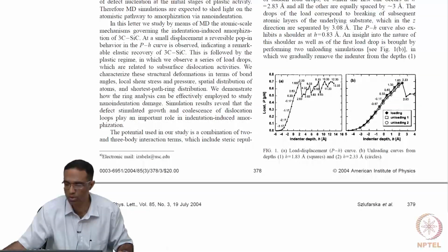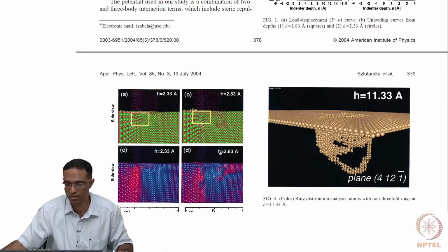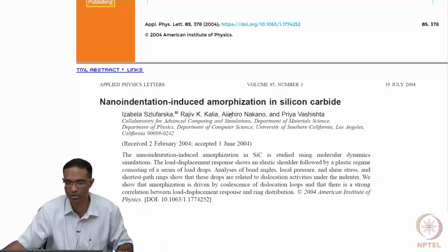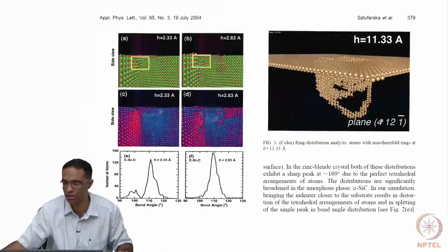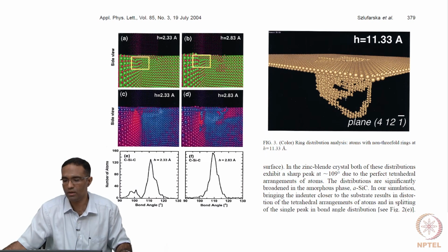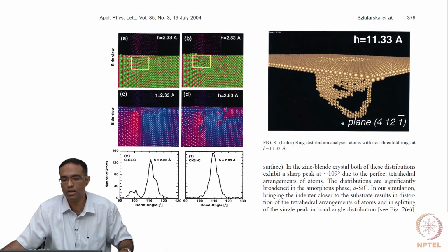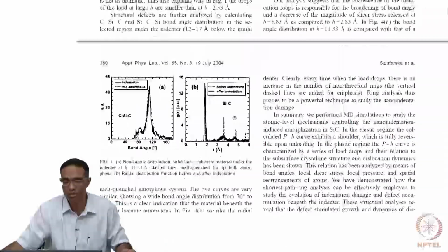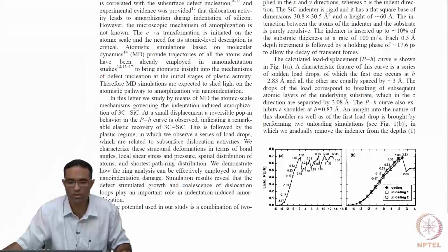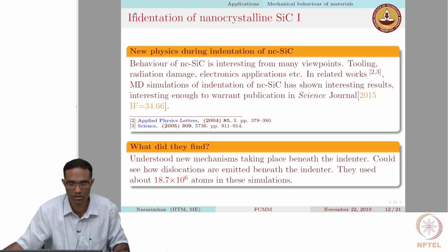So this is the load displacement plot that they have, and this is of course not really a nanocrystalline material that they have used. They have used a single crystalline material, but on performing the indentation, they have marked those atoms which deviate from their normal behavior, and they're able to look at the manner in which these dislocations are emitted beneath the indenter when they indent ceramic materials such as silicon carbide. So this is an example showing the mechanical behavior of a ceramic material.